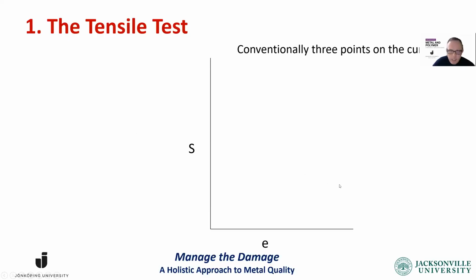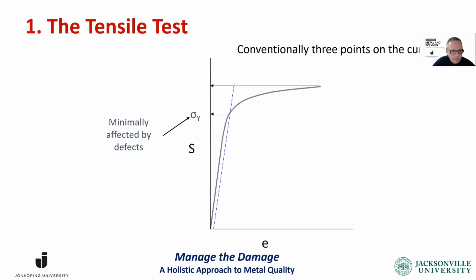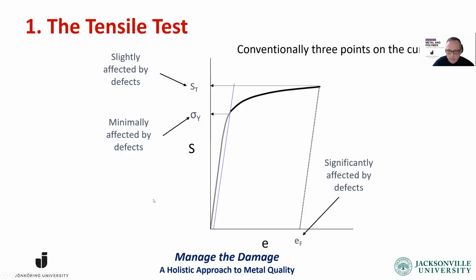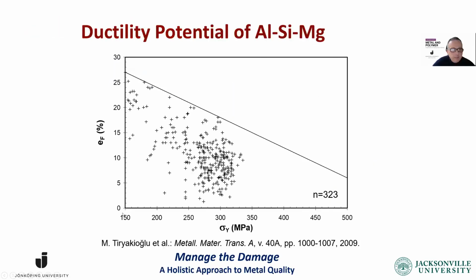So let's jump into the tensile test. Conventionally, we look at 3 points on the curve. The first one is the yield strength. The second one is the tensile stress. And the third one is elongation. Among the three, yield stress is minimally affected by defects. Tensile stress is slightly affected by defects, and elongation is significantly affected by defects. So which one are we going to use, and how is this going to look like? Before I give you the answer, let me talk about what we can actually get from the metal.